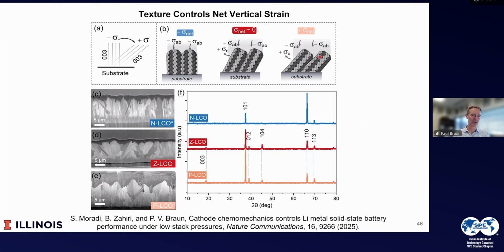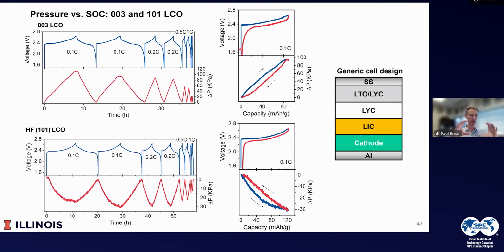And so what we found is that we could actually grow the crystal. So if we have it this way, there's going to be an expansion and contraction. But if we orient the crystal at just the right angle, we can create a system where the net strain is very close to zero. And what that means is now that the strain that the current collector is feeling, and that the separator is feeling, or in this case, the solid state electrolyte is feeling, and the anode is feeling, and the anode current collector is feeling, we can control all those strains to make them very small, or we can make them positive or negative.